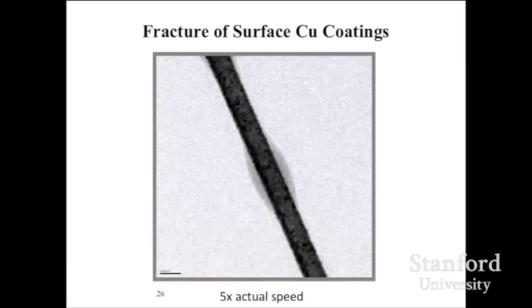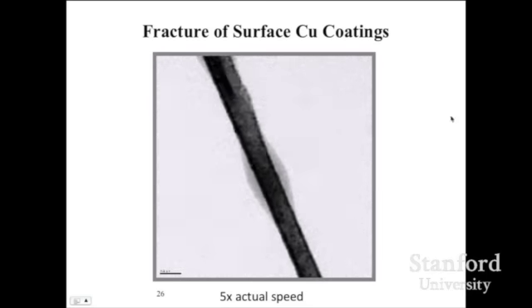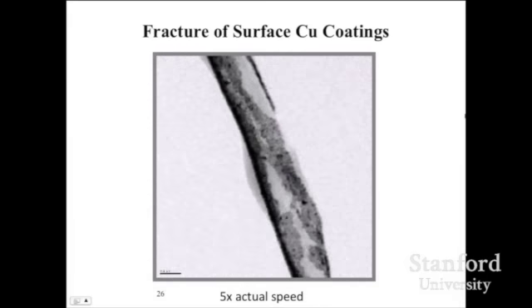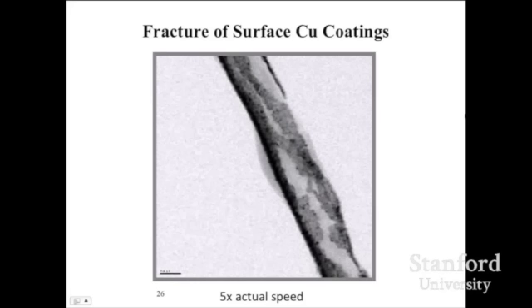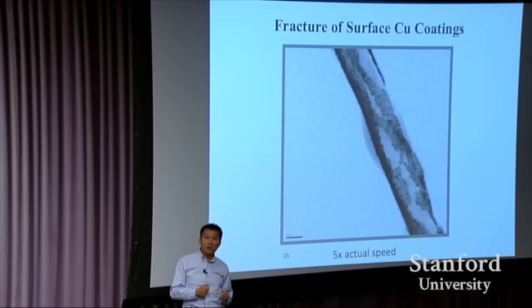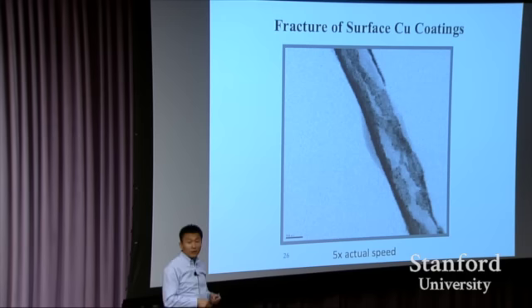Now let's see something dramatic. This is a silicon nanowire, 200 nanometer scale bar, very small, with a coating, copper, on the surface. Once you start to charge this battery, you see the volume expansion happen in a very dramatic way, and this copper coating is cracking. And nothing can stop this volume expansion. It's just so strong. There's a lot of driving force making this happen. But the nanowire itself does not break.